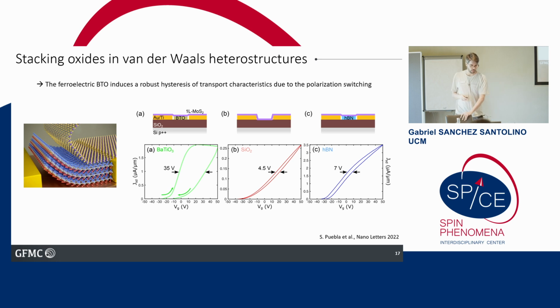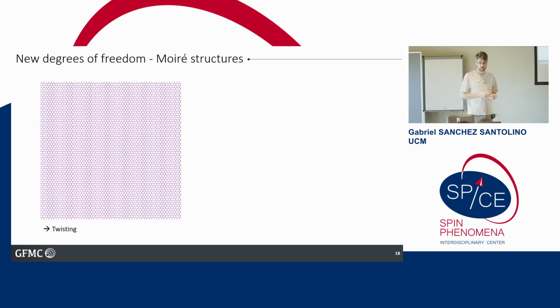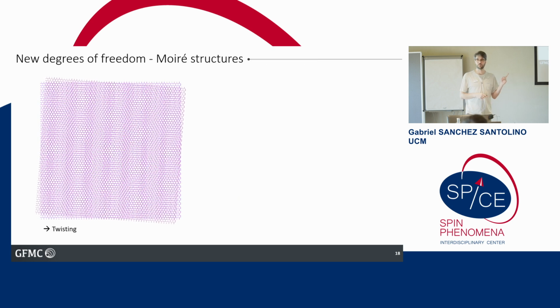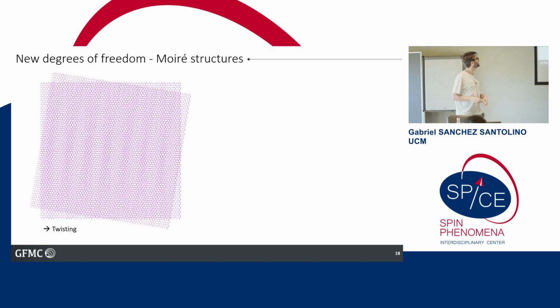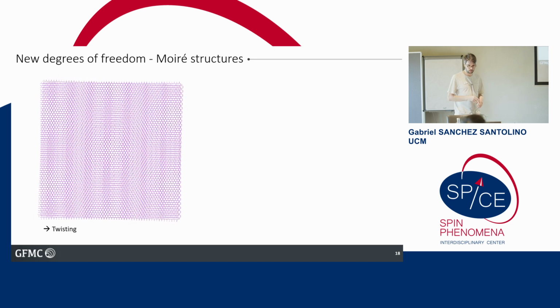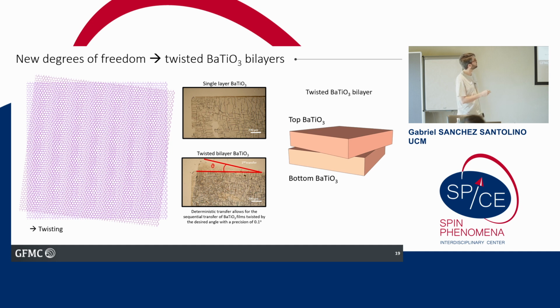But the thing that we were most interested in was starting to do this twisting. So I'm going to show the same animation that I was showing before. We can do some twisting of the layers. We are going to transfer 2 layers. This is the single barium titanate layer, which is 15 nanometers thick. This was a bit thicker one. We are still trying to optimize all the delamination and the transfer process, because we still have some cracks and some holes, but this is a 200 micron scale bar, so we can still get big single crystalline flakes, and we are going to transfer a second layer twisted by 10 degrees in this case.